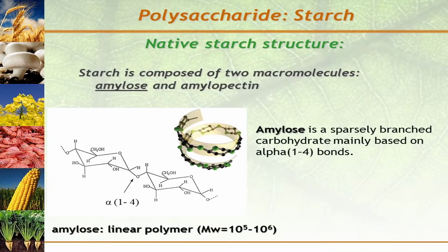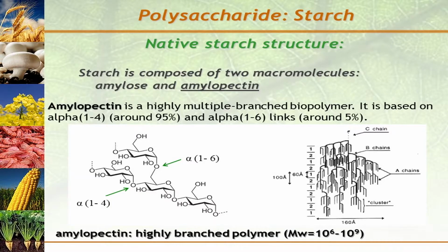So starch, as you may know, is composed of two macromolecules, amylose and amylopectin. I will not go into a lot of detail, but just say that amylose is mainly a linear polymer of sugars with alpha 1,4 bonds, and not a lot of branches. So mainly linear, with a molecular weight around a million Daltons. While amylopectin is a highly branched polymer. Still around 95% of sugars with alpha 1,4 bonds, but around 5% of alpha 1,6 bonds that you have here, responsible for this branching. So it's highly branched and gives starch this specific granular structure, where the amylopectin clusters are from here, and here you have branching and amylose chains on the other side.